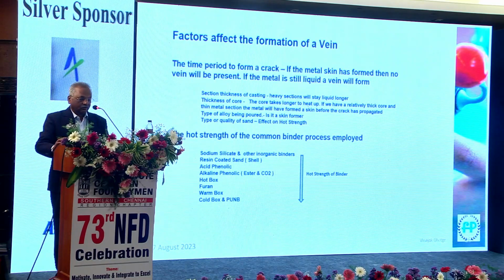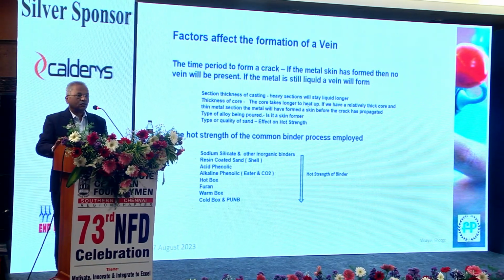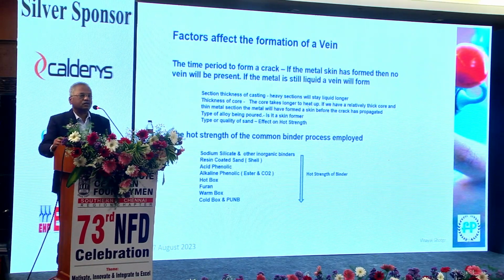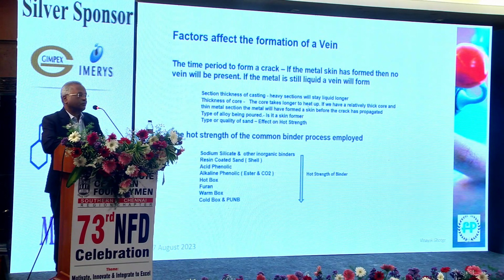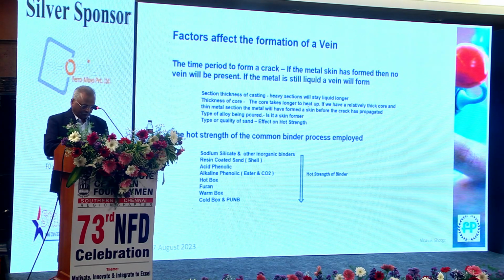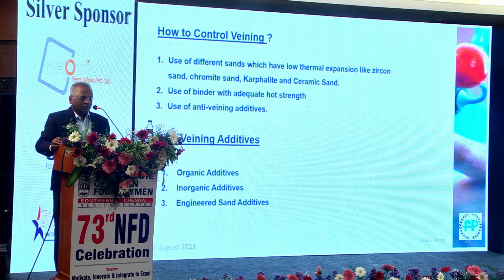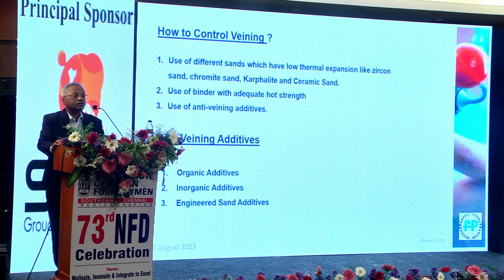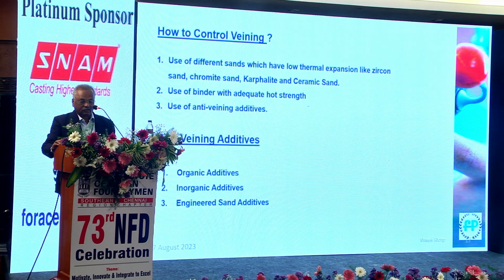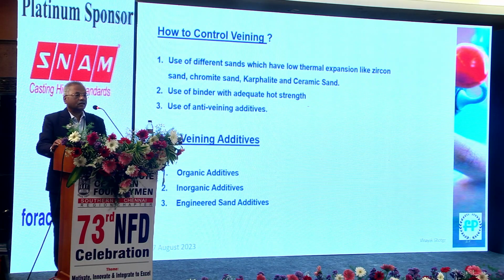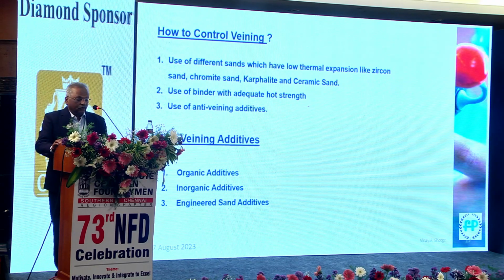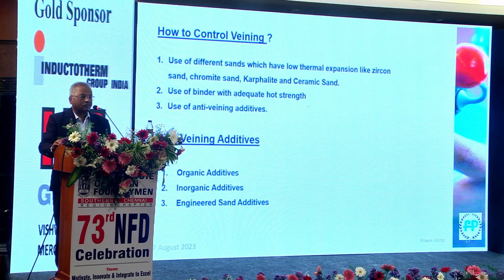So as I have told you in the beginning, the factor affecting veining is the low strength of cold box. If you compare different binder systems in terms of strength and susceptibility towards veining, as you see, the cold box is at the bottom. So how to control veining: you can use different types of sands which have low thermal expansion, like zircon sand, chromite sand, carphalite or ceramic sand. Use binder with adequate hot strength, and use anti-veining compounds or anti-veining additives. The anti-veining additives are of different types: organic, inorganic and engineered sand additives.